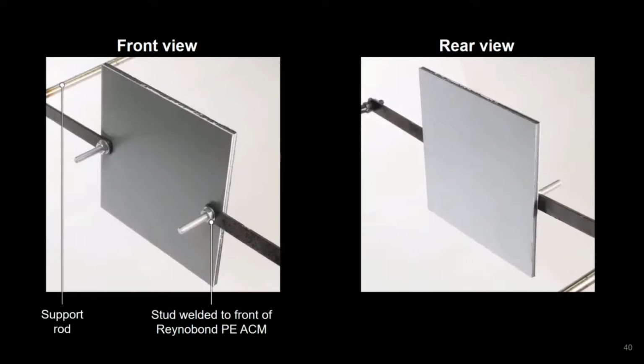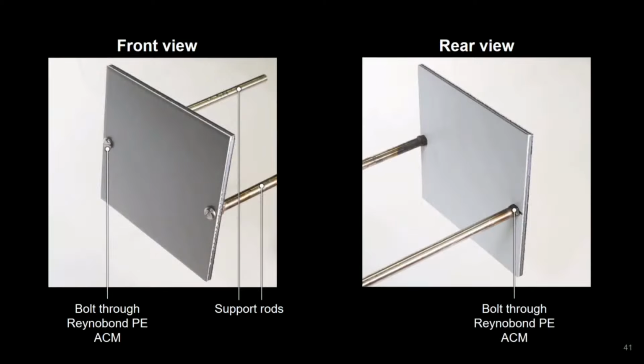We also used a front fixing condition, shown here, with the sample supported from its front aluminium facer, thus allowing for downward mobility of the rear face of the sample on heating. And finally, a through fixing condition was also used, with the samples drilled through and supported from both of their aluminium skins, the front face and the rear face, as shown here, thus preventing downward mobility of either of the aluminium skins and also restricting to some extent their mechanical separation on heating.